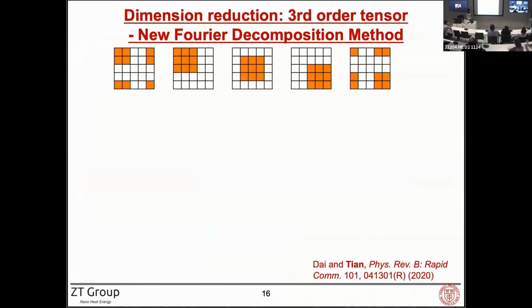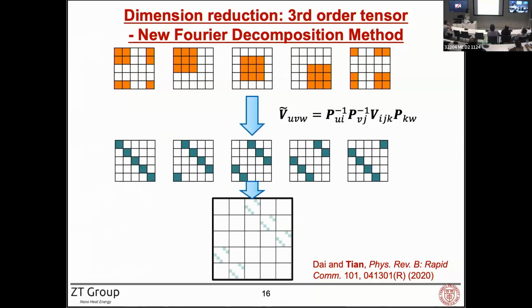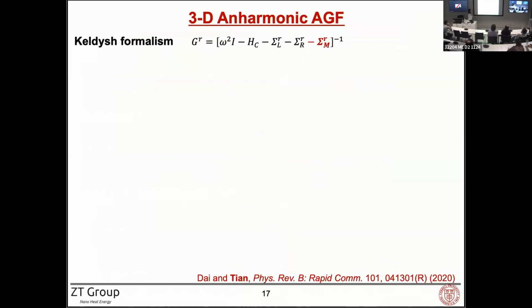When we looked deep into this problem, we realized one main challenge comes from the third-order tensor. You couldn't really see any pattern, and it's a very large tensor. In real space, it depends on three vectors. We tried to reduce this computational load by introducing a new Fourier decomposition method. With this, we were able to convert the problem into the reciprocal space, where it only depends on two wave vectors. It dramatically reduced the otherwise prohibitive computational load and allowed us to include the third-order force constant into the framework. So we now revisit this retarded Green's function.